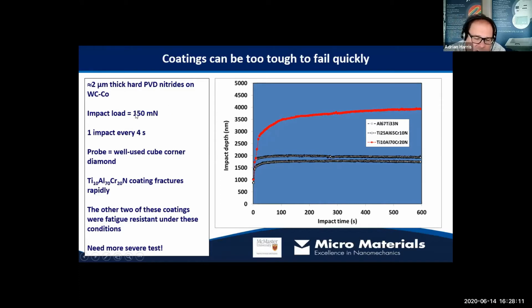And we're using in this test 150 millinewtons, and we're using a cube corner indenter. I made the point that it's a well-used one because very, very sharp indenters can blunt in the first few impacts. So this tip has worn a little bit, but to the degree where its geometry remains quite stable throughout many tests. And so really this is defining pretty much the upper extreme of what we can achieve with nano-impact testing. As we can see, it's not capable of failing these coatings. So the conclusion is that we need a more aggressive and severe test.